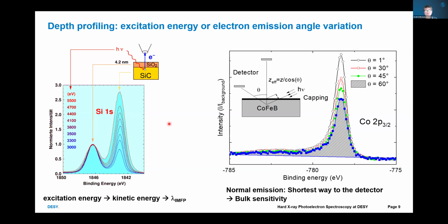And the second possibility to do depth profiling is to change the takeoff angle of the photoelectrons by simply rotating the sample about the surface. The trick is that if the sample is perpendicular to the analyzer, grazing incidence, normal emission, then the electrons travel the shortest way to the detector. In this way, we have bulk sensitivity. And if we rotate the sample, then the electrons have to travel longer to the detector, and this enhances the intensity from the capping layer, from the surface.